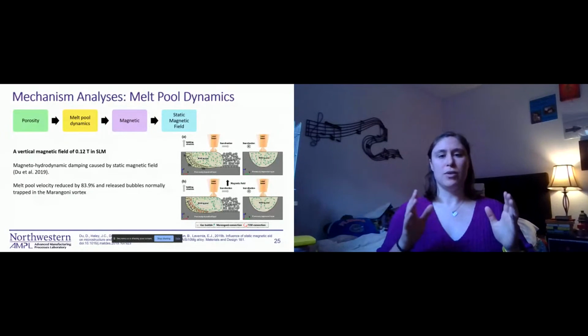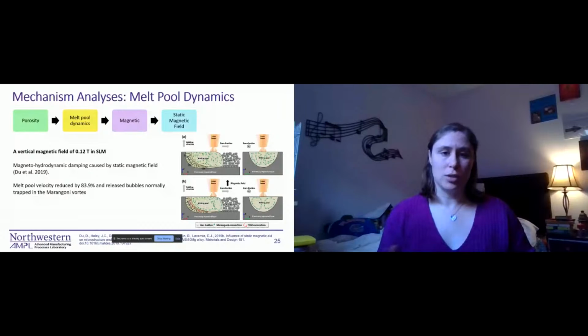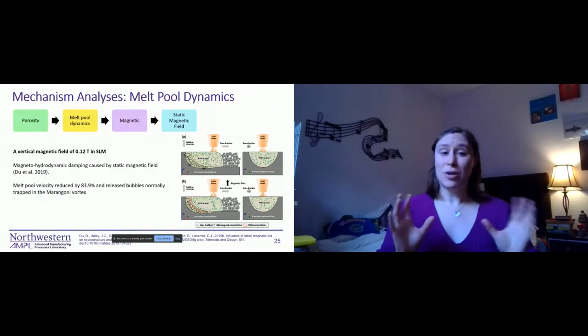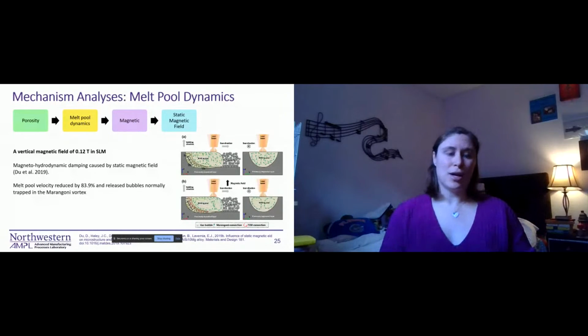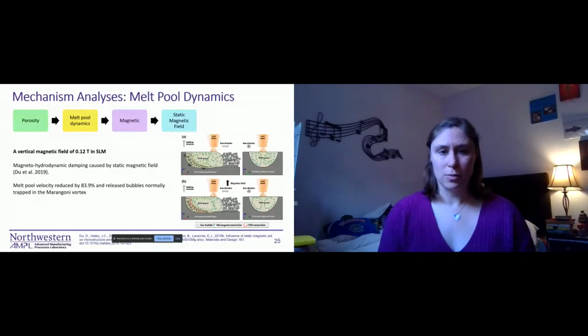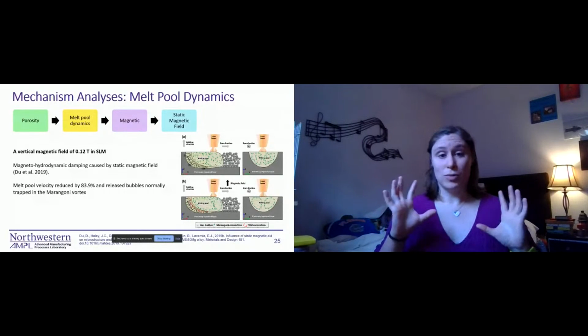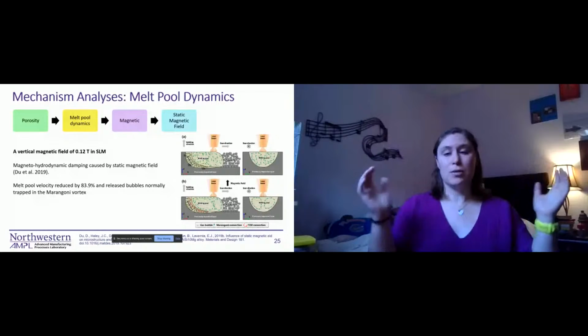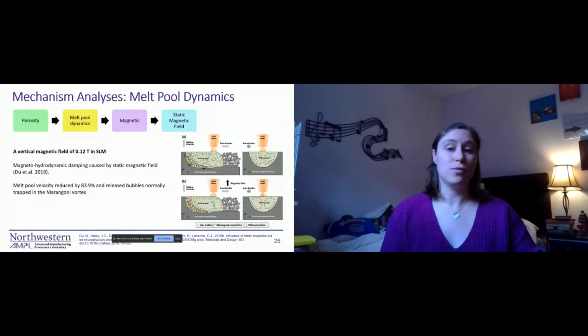So normally we have very strong Marangoni convection in the melt pool in metal AM processes. Magnetohydrodynamic damping can actually reduce that velocity. So in this case, the melt pool velocity was reduced by about 84%. And it allowed bubbles to be released rather than trapped in the Marangoni vortex.